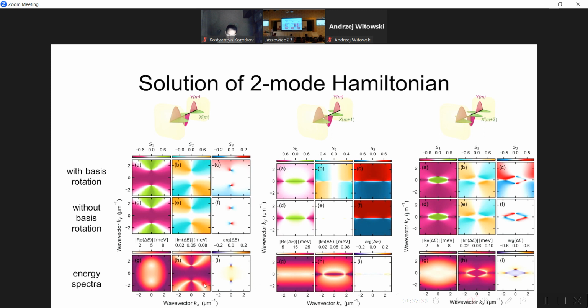In this case, we see an exceptional point because our Hamiltonian fulfills PT symmetry, and of course, it's not a Hermitian Hamiltonian. For example, if you look at this panel, you see that if you don't take into account the rotation of bases, you cannot generate the S2 Stokes polarization parameter, and in addition you cannot generate the change of sign for the S1 Stokes polarization parameter.